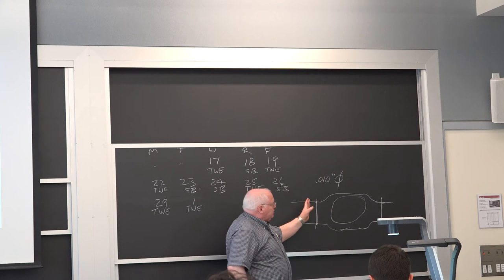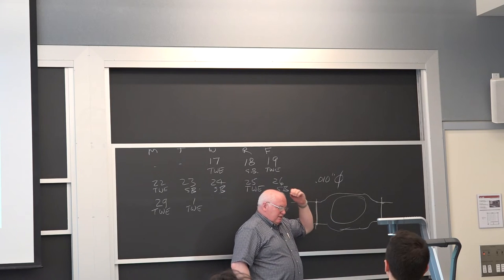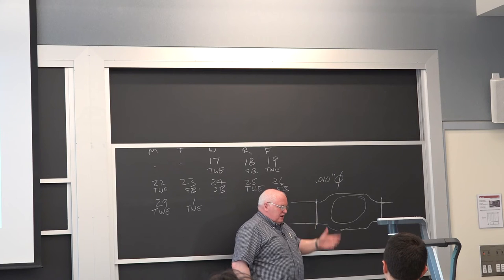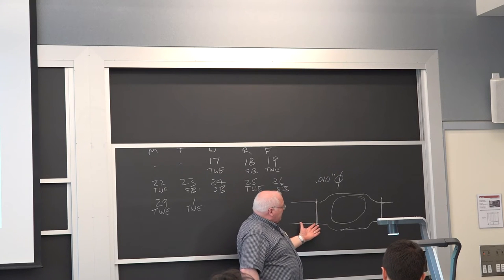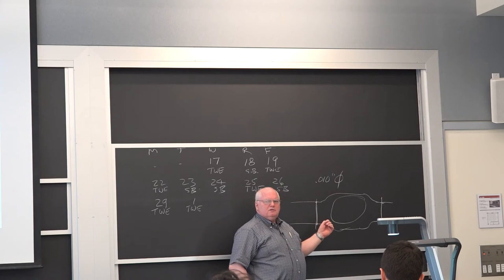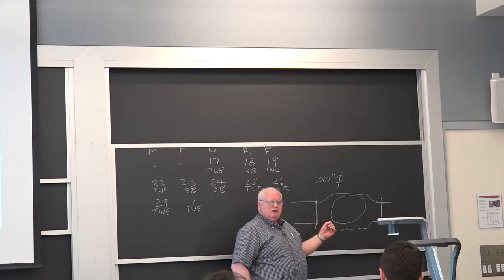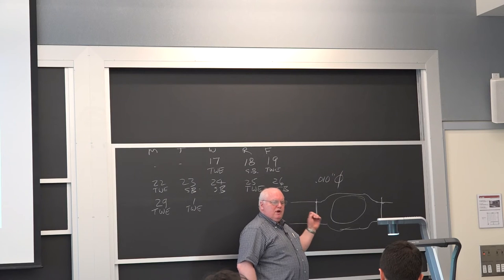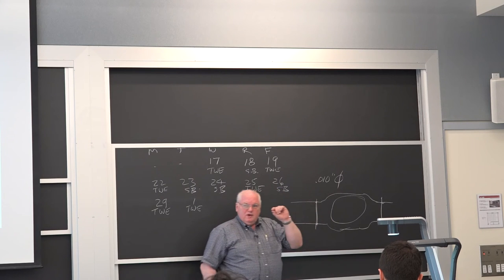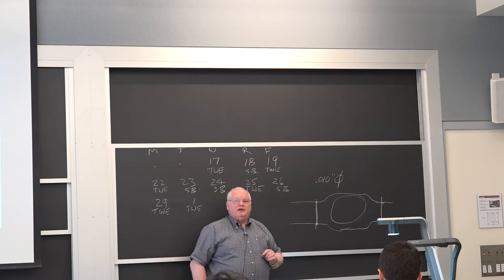So Engelhard was having to weld this out of titanium, and they hadn't done a lot of titanium welding before, and they were getting a failure on, I think, half their welds on the X-ray. They would find some little pore in there, okay?